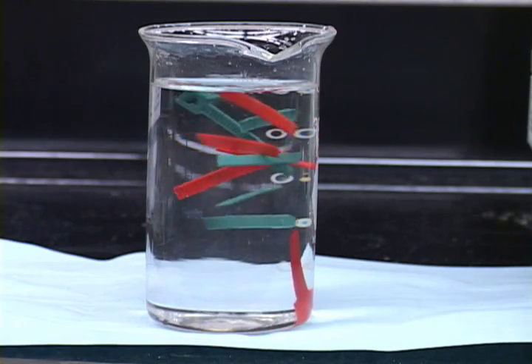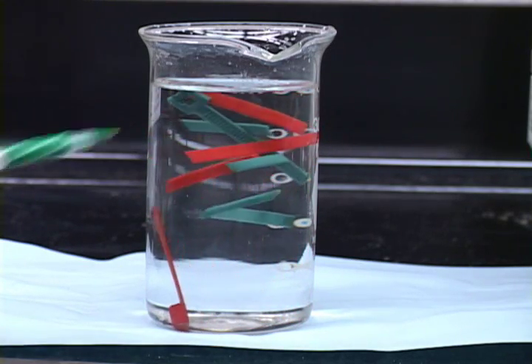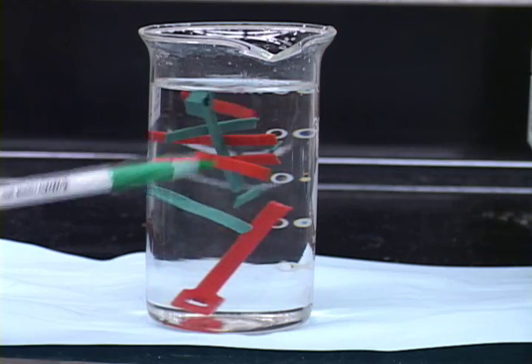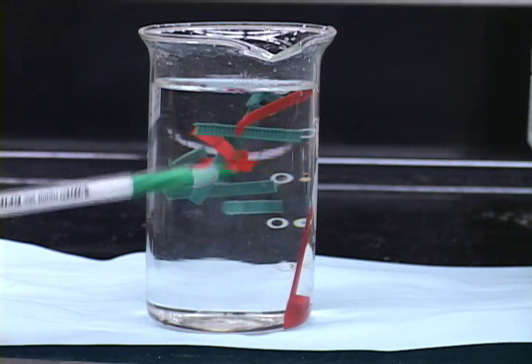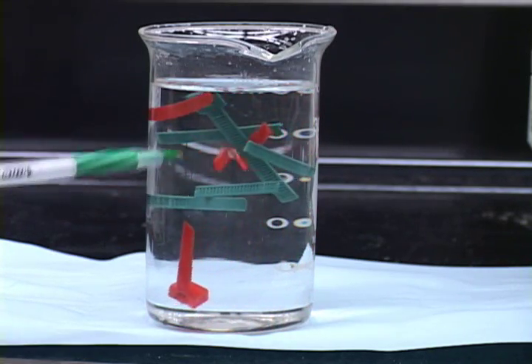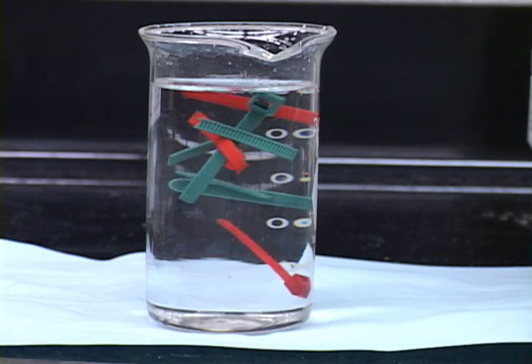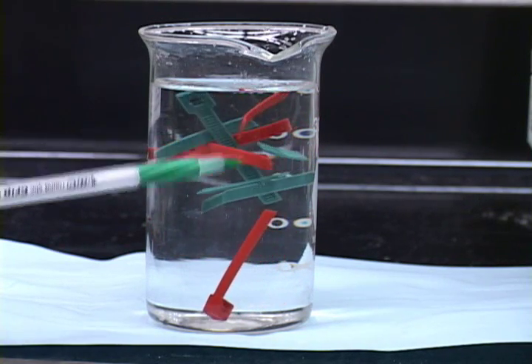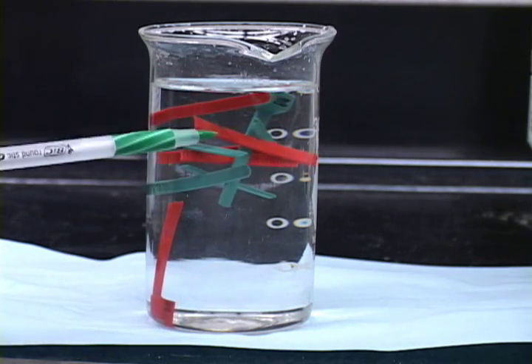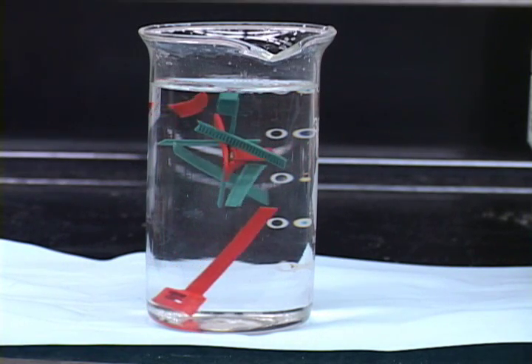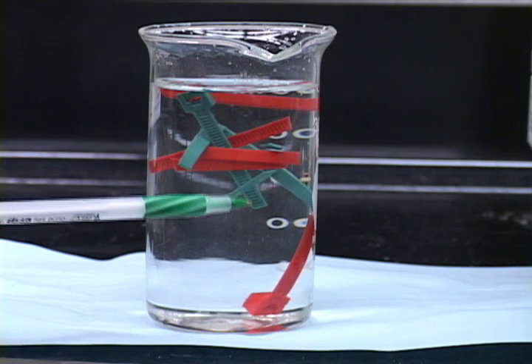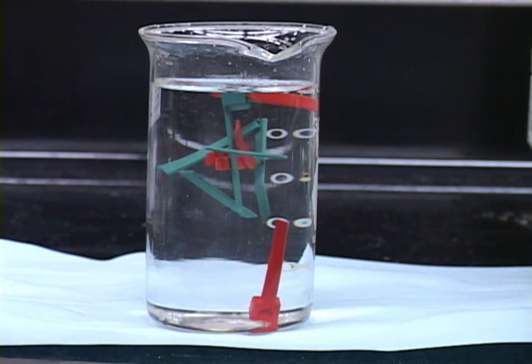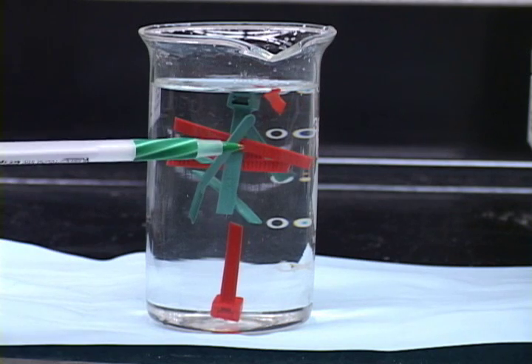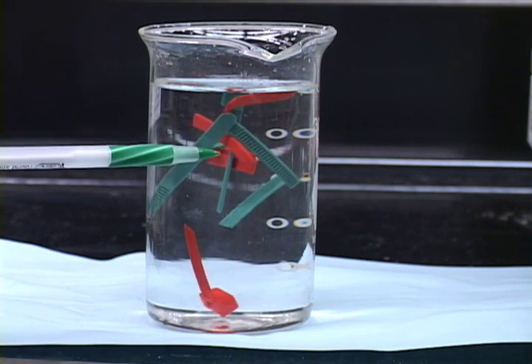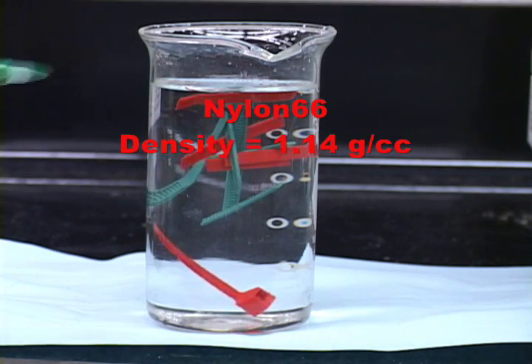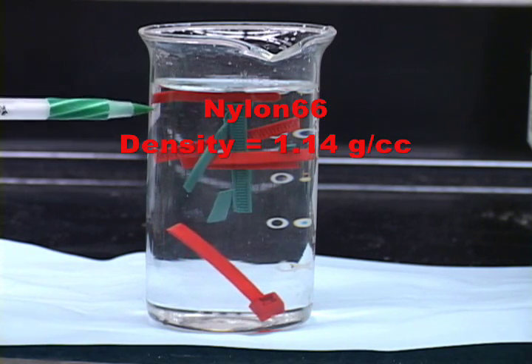In another example of the use of flotation to measure density, we have here some plastic which we have suspended in a solution of sodium sulfate and water, and then we have adjusted the density of that sodium sulfate solution until the unknown neither sinks nor floats on average. And then we have measured the density of the solution by pipetting out 10 milliliters and weighing it. The density of this solution is 1.138 grams per cc, which is also the density then of the plastic.